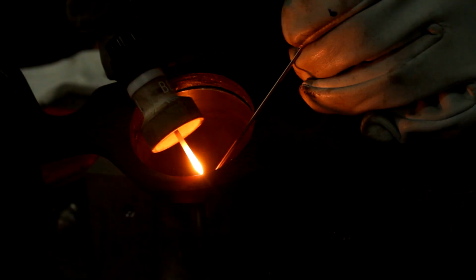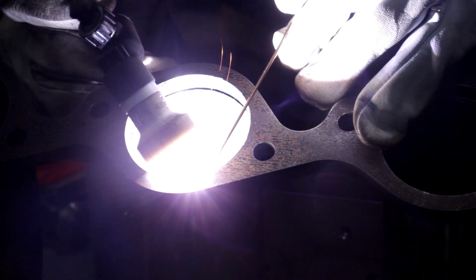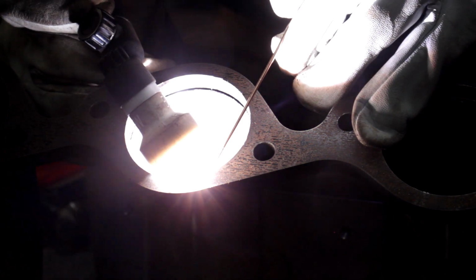Now what you see here is that if you notice in the weld, I actually caught what at the time I thought was a gust of wind, but it was actually the cap on the inside, or the screw where it connects to my line, was loose. So it pulled in a little bit of oxygen. I had a little bit of porosity there, and anytime you get porosity, you have to grind it out.